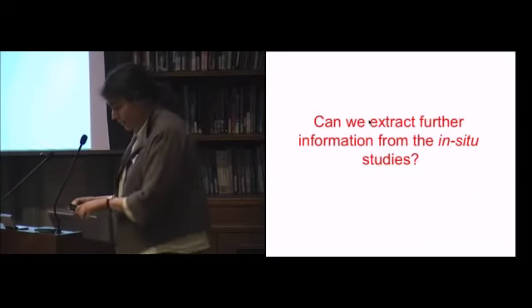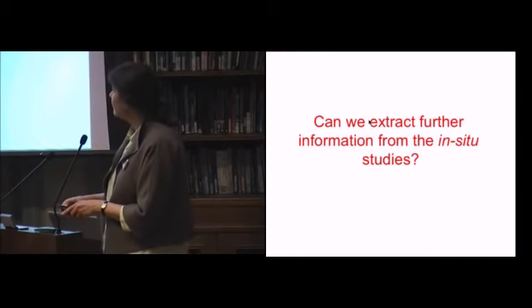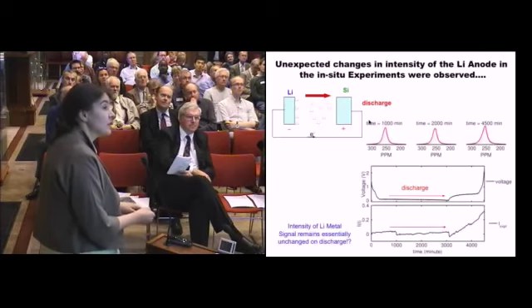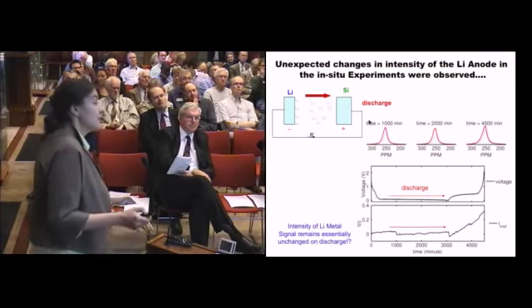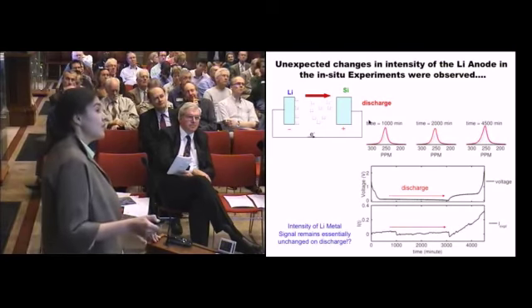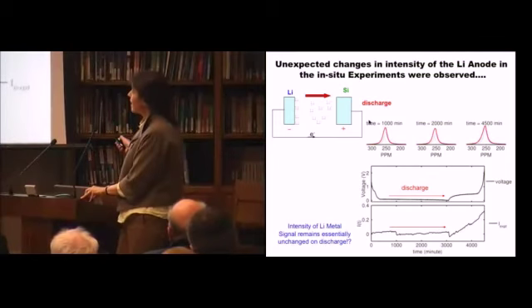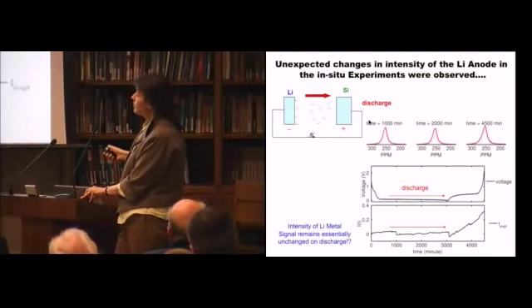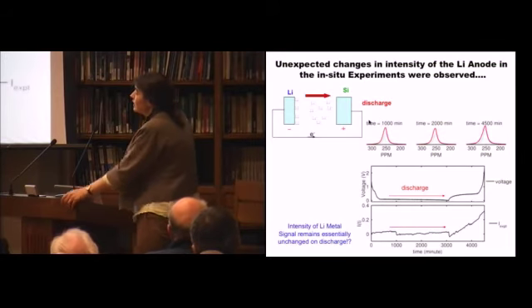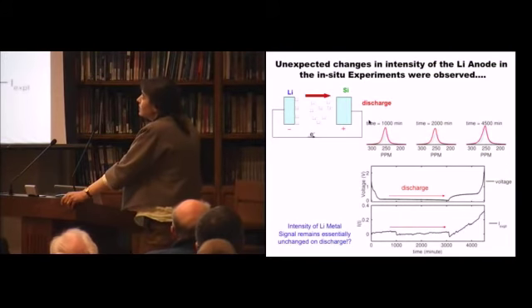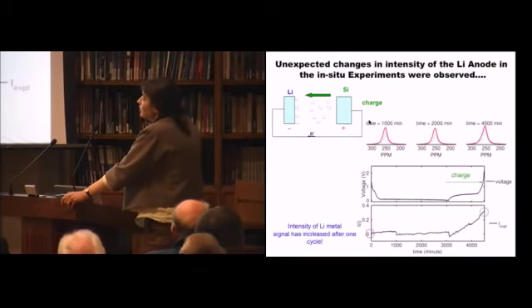So just in the last few minutes, to think about other information we can get from these in situ studies. So I focused on the silicon, but if you look at the lithium, it is a metal and it has a peak at about 250 ppm. And when you discharge your battery, the lithiums go from the lithium to the silicon, so this is the discharge. And if you look at the intensity of the signal, it really didn't change very much. But on charge, you pull the lithiums out of the silicon, they go back, and now the intensity increases.